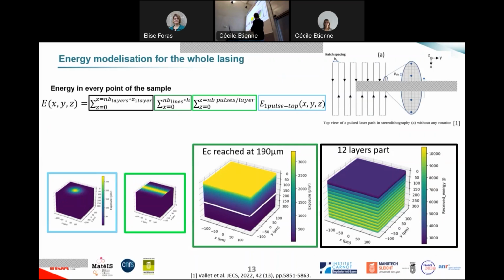After that, you see this kind of pattern when you add all the layers on top of each other. What can be a bit surprising at first is that you have lower energy received on top than on the lower sides, because we added the energy each time. This is very important for the characterization of polymerization. If we do analysis on the top of the sample or in the middle of the sample, we won't have the same conversion rate, and we need to achieve the highest conversion rates of our polymers to avoid a bad debinding, where we could have some thermal polymerization or some cracks due to this difference of conversion between our polymers.